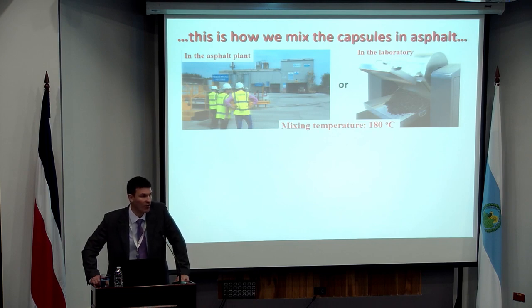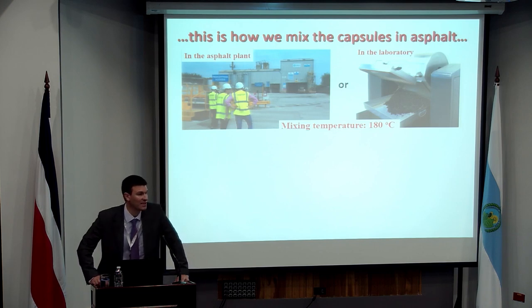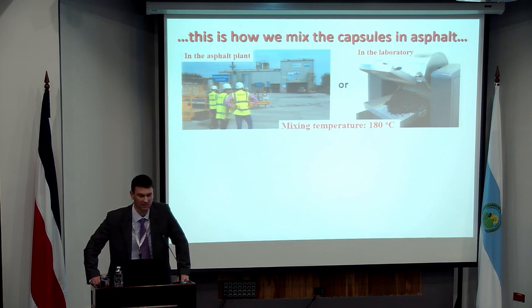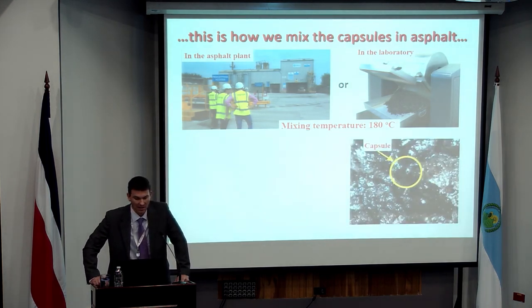They are already adding these capsules to some of their materials. They are quite robust in terms of their early life. You can add them to a normal asphalt plant, or you can make them in the laboratory up to 180 degrees C mixing temperatures and obviously compaction energies. We can identify them if we look under X-ray CT or under SEM, some kind of microscopic analysis. We can see them.